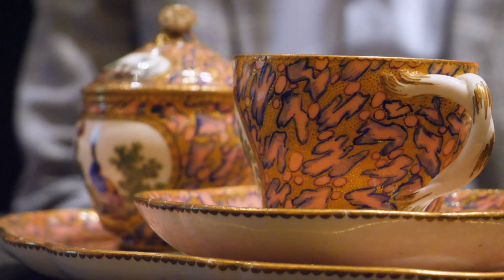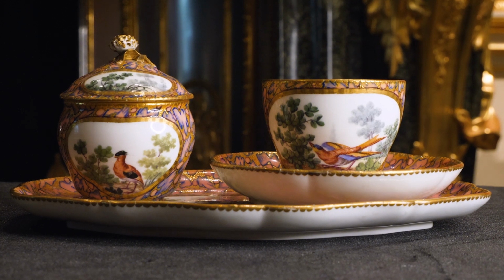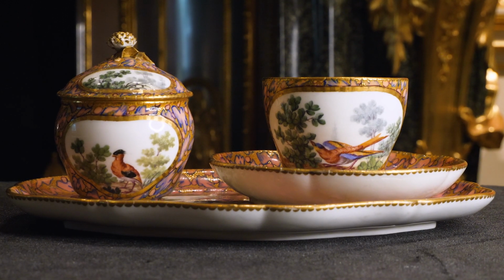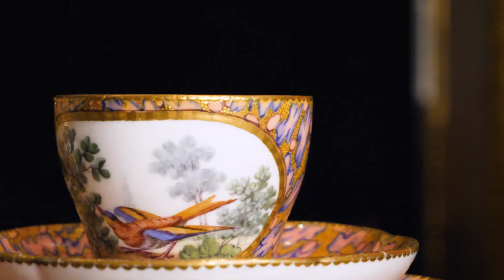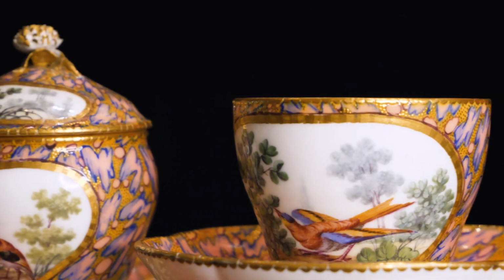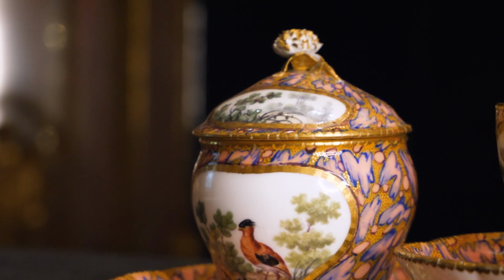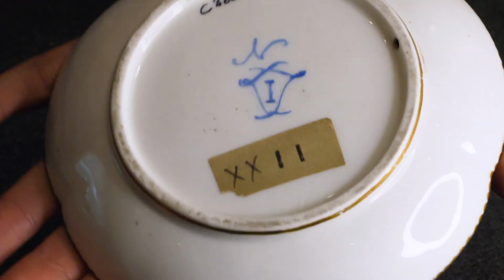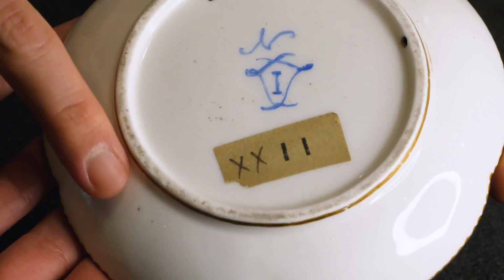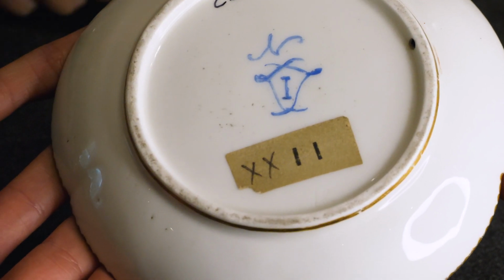After drying, the pieces were fired in the kiln for the first time at about 1200 degrees Celsius, protected by clay domes. Of course, in the 18th century, there were no accurate means to measure the kiln temperature, and officials had to rely on experience and empirical observation, such as calculating how much wood they had already burned, or the color of the flames. The first firing resulted in a matte and unglazed finish known as biscuit, a finish that can be appreciated on the unglazed edges underneath.